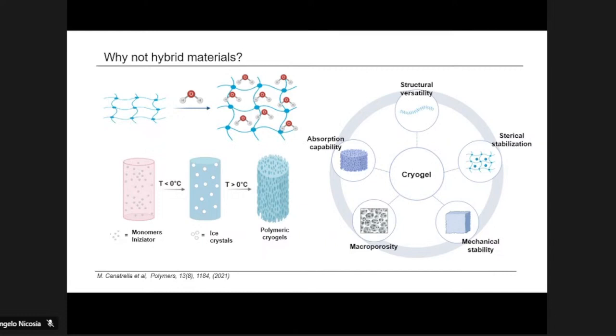cryopolymerization. Cryopolymerization is a reaction conducted at a temperature below the freezing point of the solution. During freezing, we have the growth of ice crystals inside the structure, and during the thawing phase, the crystals melt, and therefore we have porosity in the final material. And therefore we have a sort of different properties derived from these types of materials.